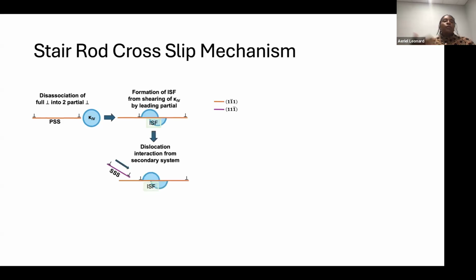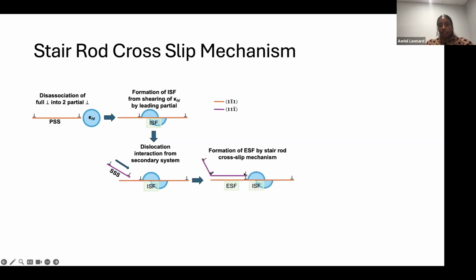As we keep progressing, we know from our material that we have activated secondary slip systems. So now we have a secondary slip system coming, and we have two partial dislocations. It's energetically unfavorable. So what the first partial does is it creates this sessile stair-rod dislocation here, and then it cross-slips to the plane above. And so that creates an extrinsic stacking fault.